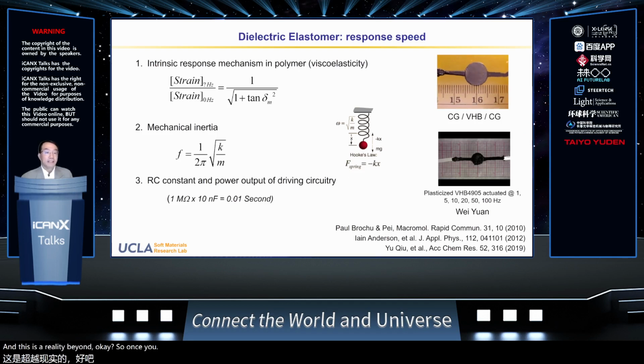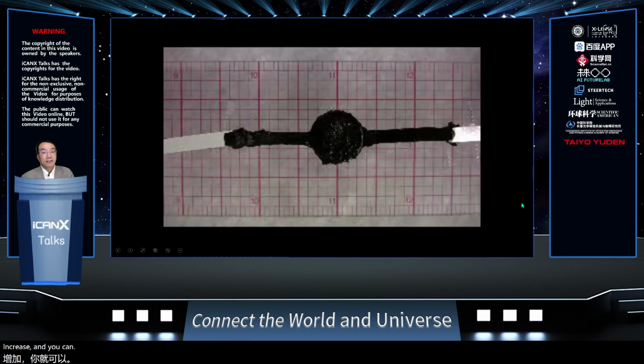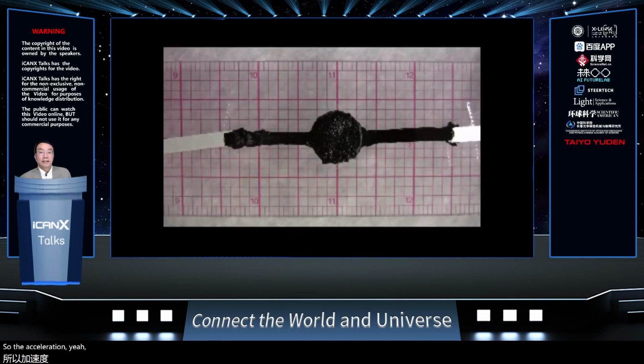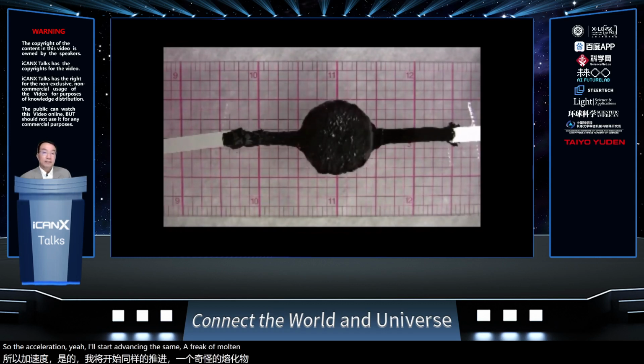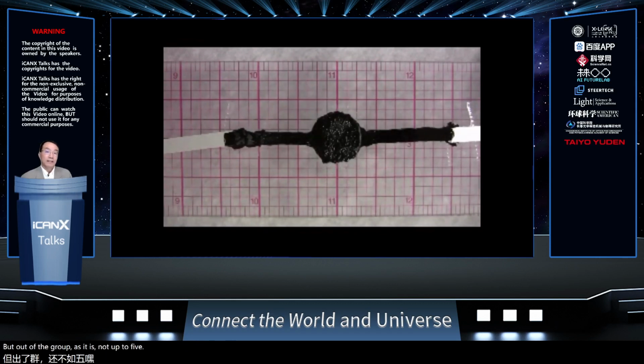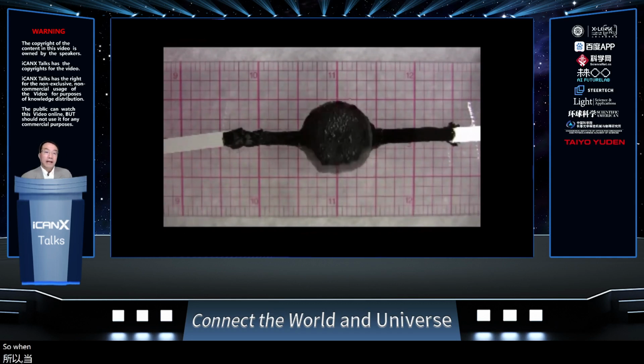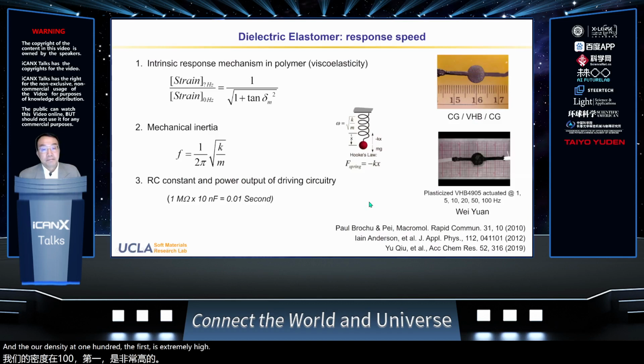Once you plasticize this VHB, in a way spraying a plasticizer like DOP, dioctyl phthalate, into this polymer to reduce the viscoelasticity, you will see that its response speed can be significantly increased. Let me play this video here. The actuation starts at 1 hertz, at the same peak voltage, and the frequency is ramped up to 5, 10, 20, 50, and 100 hertz. With the dielectric elastomer film at about 100% area expansion here, the power density at 100 hertz is extremely high. So that shows that when the viscoelasticity is removed, the dielectric elastomer can respond with a high actuation strength at a high frequency.